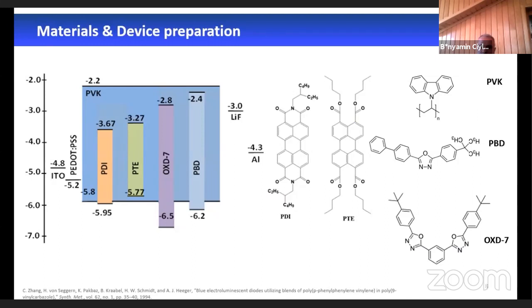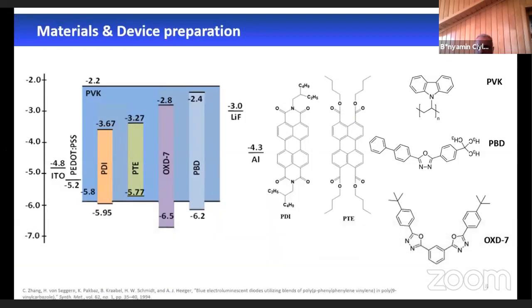Materials and energy diagram can be seen at that slide. We used PDI for orange-red emitting material and PTE for green emitting material. We used PVK as a host and hole transport material, and two different electron transport materials, PBD and OXD-7, were used to balance the electron and holes in the active layer.